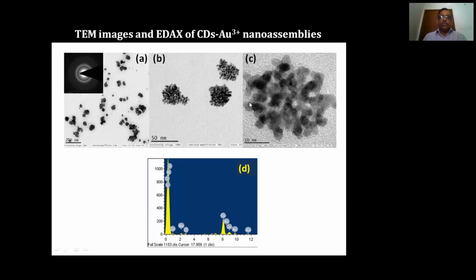Now for the TEM images, as you add the gold solution to the CDs, you can see the assembling or aggregation of the carbon dots happening.